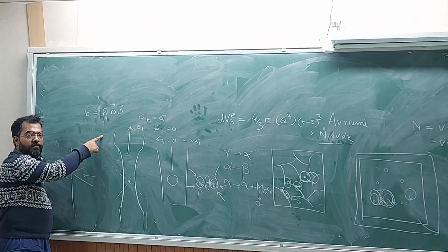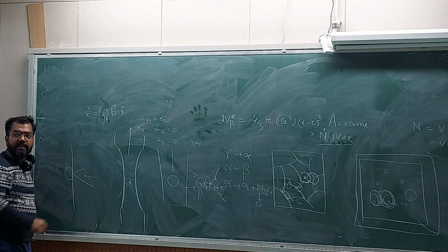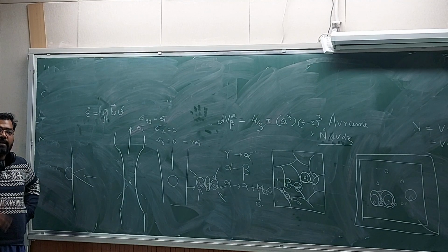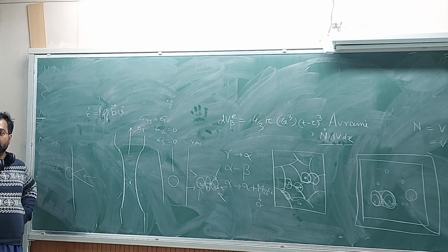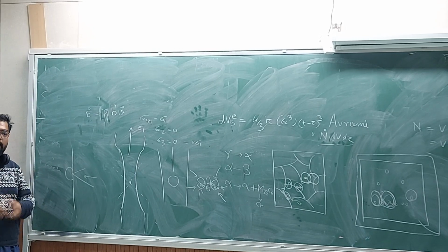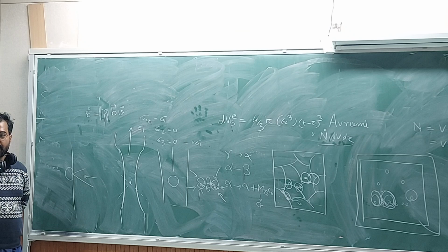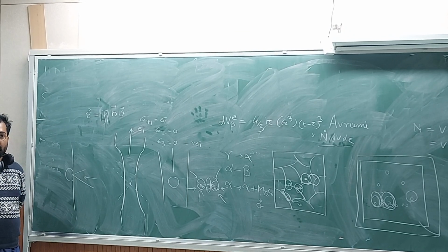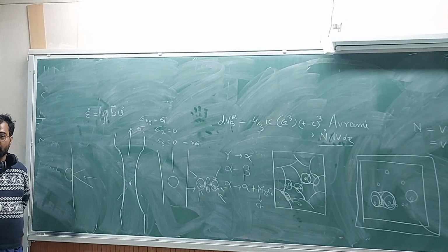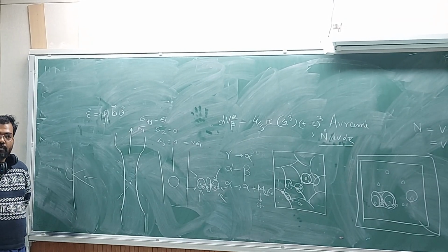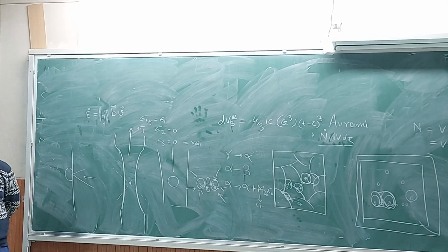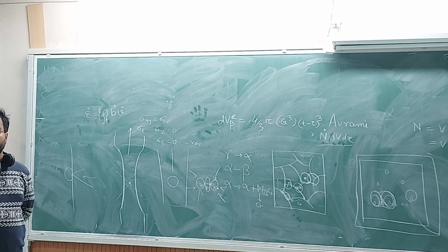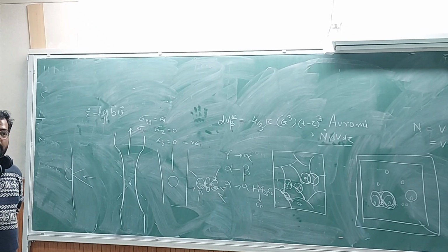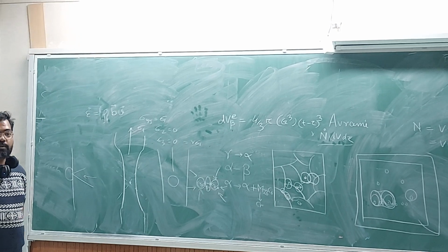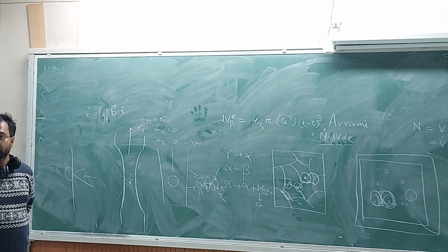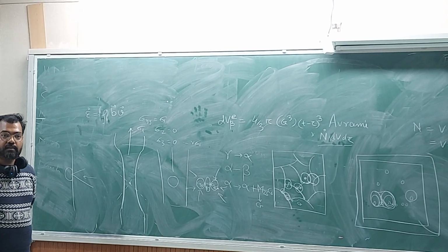With an increase in strain rate, dislocation density cannot decrease unless you provide thermal energy so that there can be annihilation, where two dislocations merge together and vanish. There are no other ways of decreasing dislocation density from the point you began to deform the material, unless you heat it, unless there is a recovery or recrystallization. If those things are not happening, dislocation density will not decrease. So what will decrease? Dislocation velocity will decrease. Right? Burgers vector you cannot change.